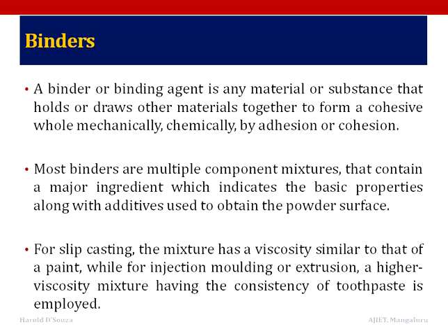Thermoplastics allow the mixture to flow easily on heating and become rigid on cooling. Candle wax is a common thermoplastic binder. Wax polymer mixtures are widely employed in powder shaping technologies because of the low cost, easy processing, and lack of hazards. A mixture of 2/3 paraffin wax and 1/3 polypropylene can be molded between 110 and 150.